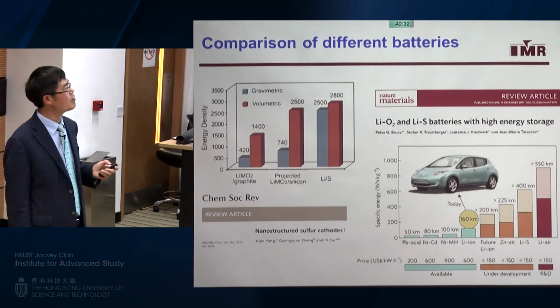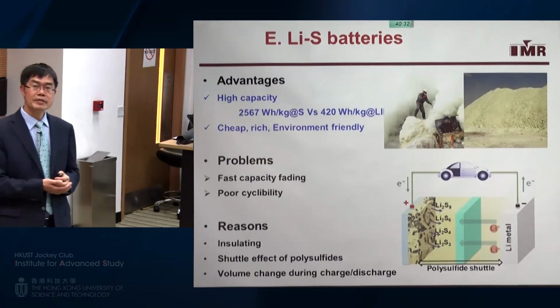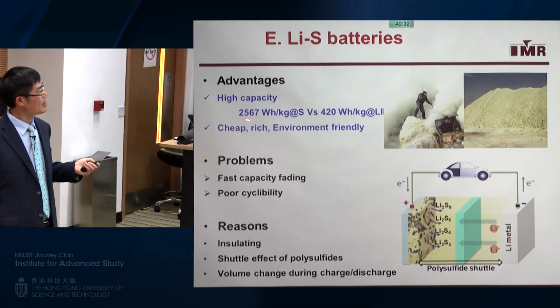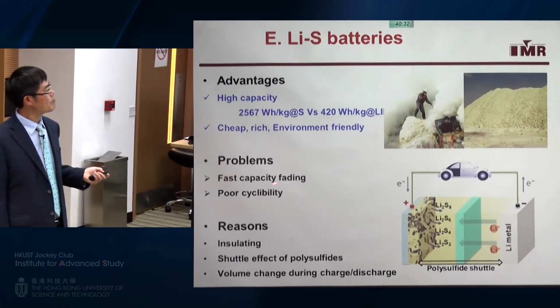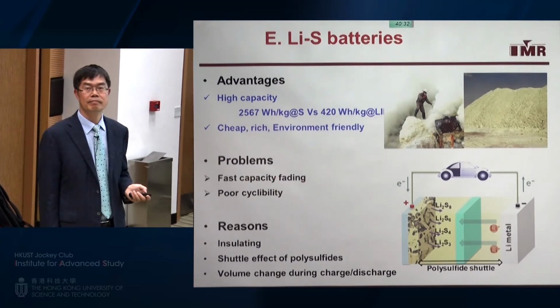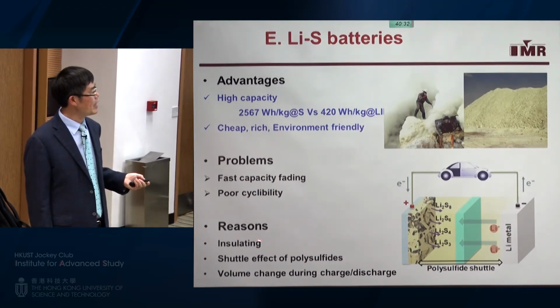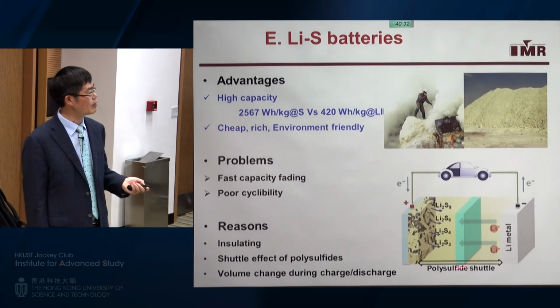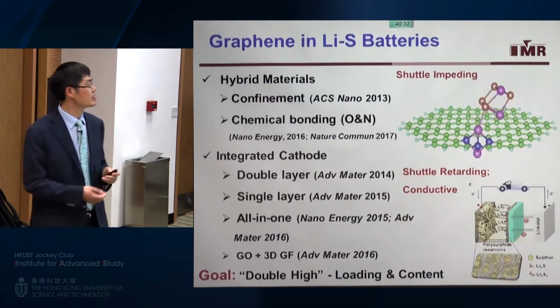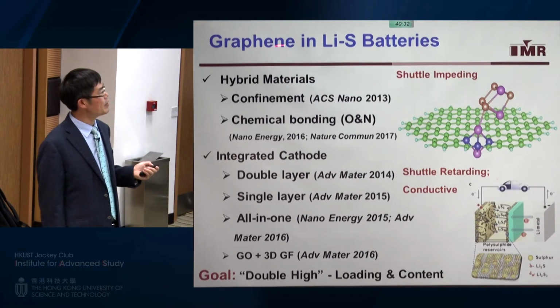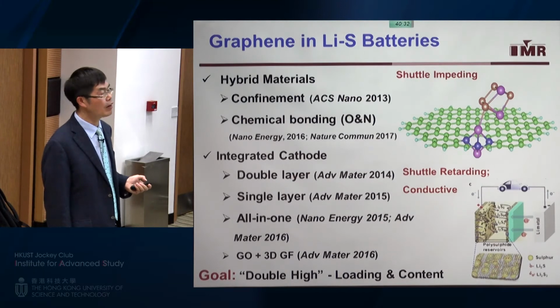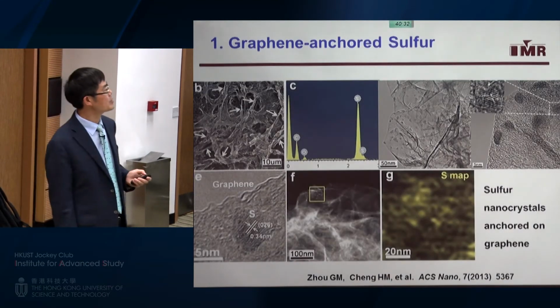Lithium sulfur batteries have very high capacity, and also the cost is not much. But the problem is very fast capacity fading or poor cyclability due to the insulating nature of sulfur, and also the shuttle effect of polysulfides between the cathode and anode, and also, again, volume change during charge and discharge. So then we try to use graphene in lithium sulfur batteries by different approaches, including confinement and chemical bonding, or simply changing the configuration of the electrode. So I will show you some examples.